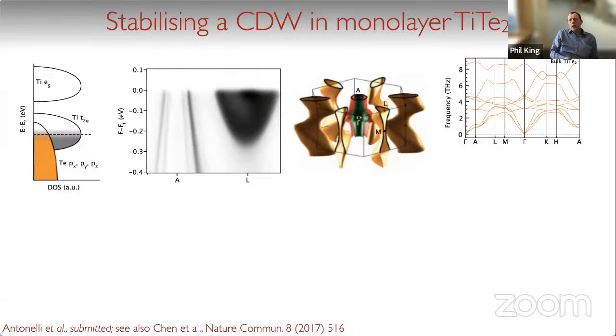Now, this is the sister compound to titanium diselenide, and titanium diselenide is a very famous material for a 2x2x2 charge density wave that it hosts in the bulk, and there's been a lot of discussion about the mechanisms of that charge density wave. But in titanium ditelluride, the band overlap near the Fermi level is much larger than in the selenium compound, and this is thought to completely destabilize the charge density wave instability. And indeed, in the bulk, no charge density wave is seen.